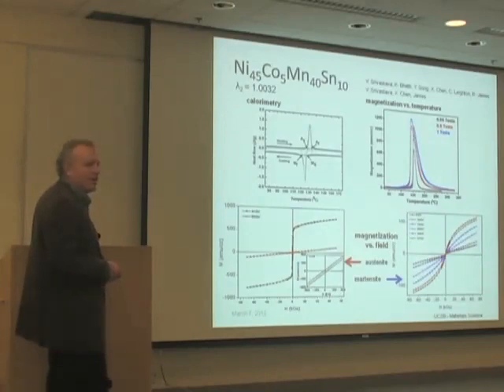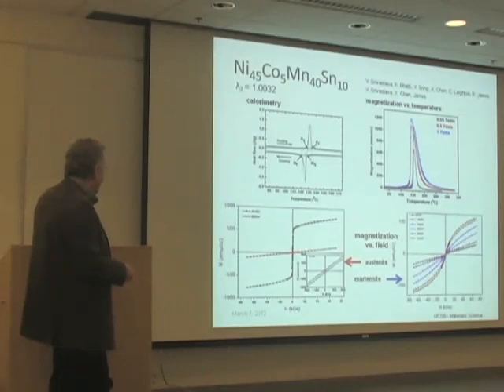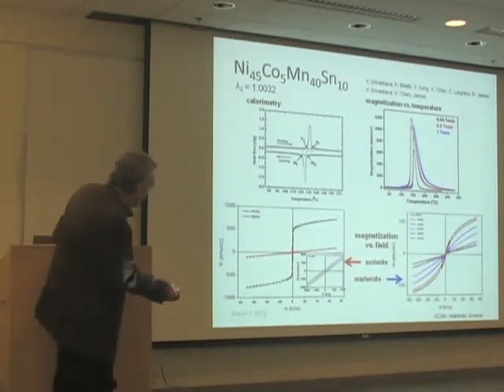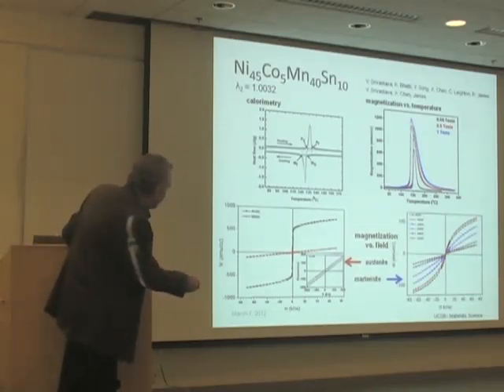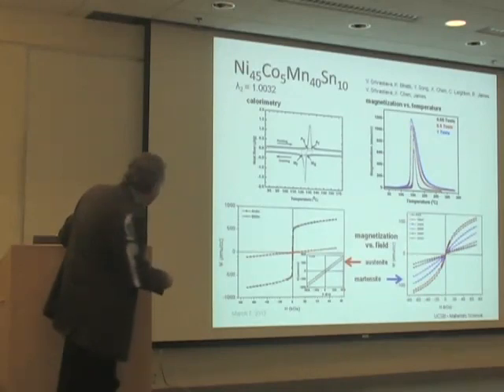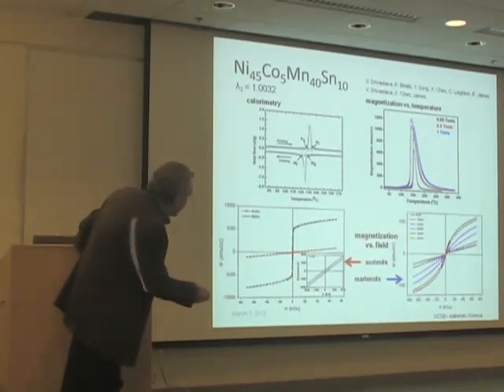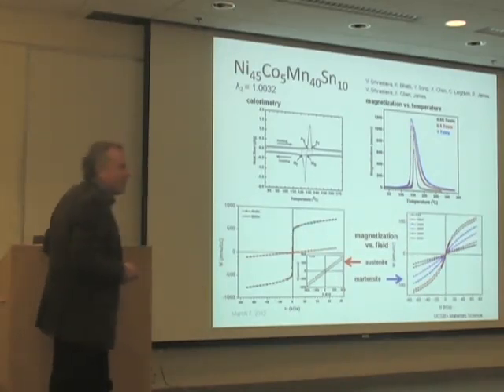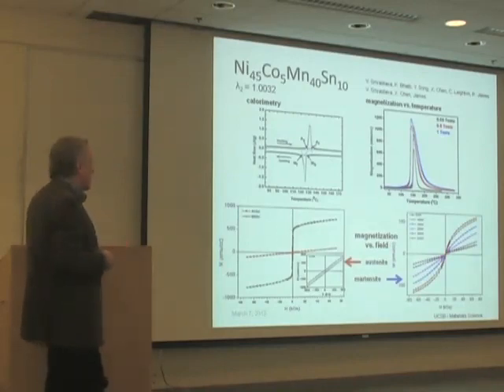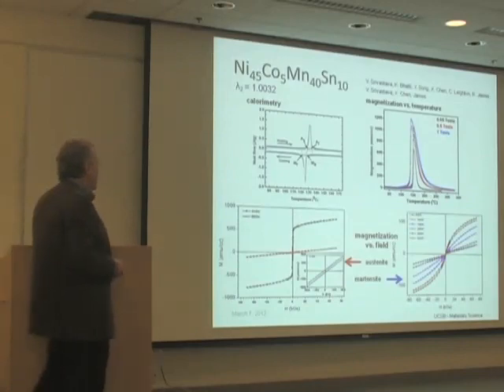That's the magnetization curve. This is magnetization versus field. This is martensite here, in austenite. Actually, if you look closely at the martensite, notice that this axis is completely different from this axis. There is a tiny ferromagnetic component. So there's probably some magnetic particles there, and we're trying to understand that a bit better. But the main thing is there's a huge change in magnetization, and it's a quite soft magnetic material.